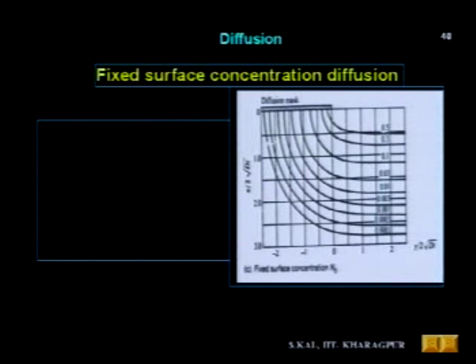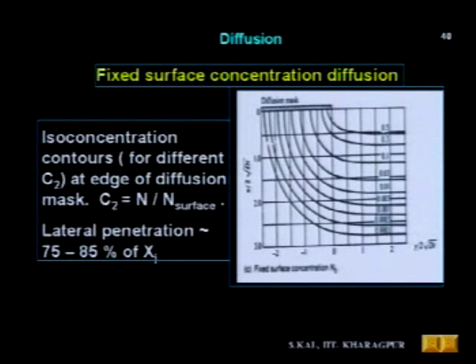Another profile is something like this. This is fixed surface concentration diffusion. And here also iso concentration contours. And here you can see lateral penetration is of the order of 75 to 85% of xj. Okay. With this, let me stop here.